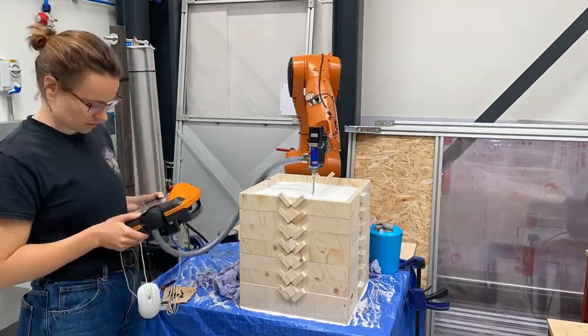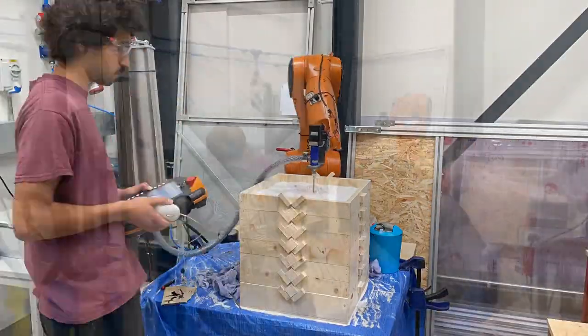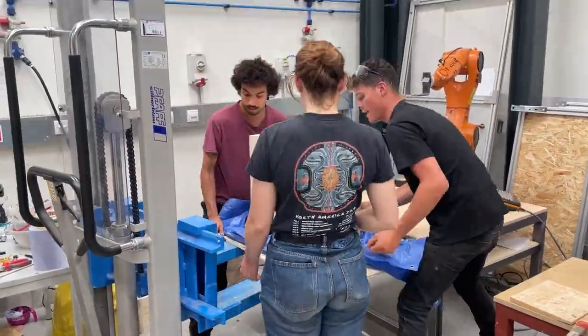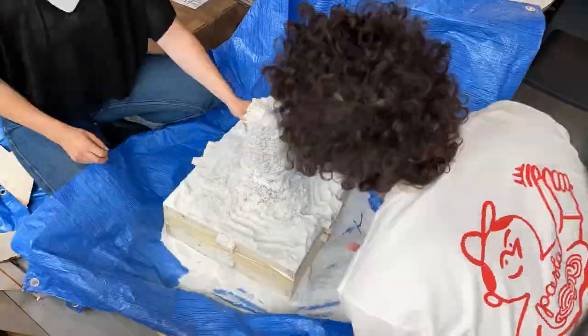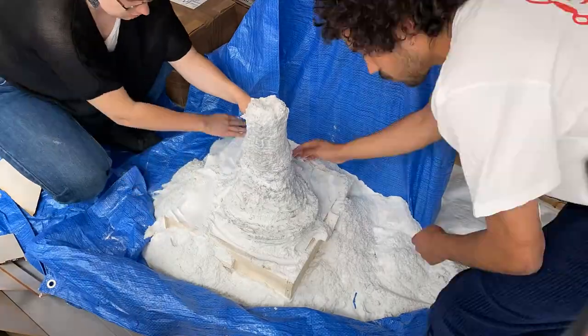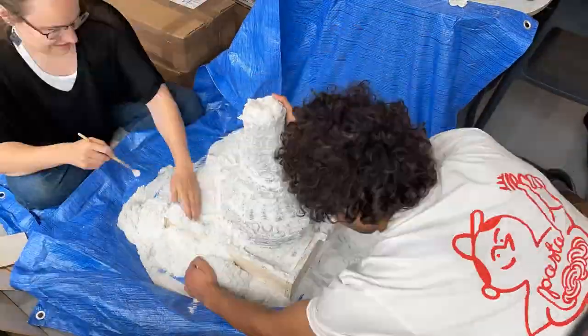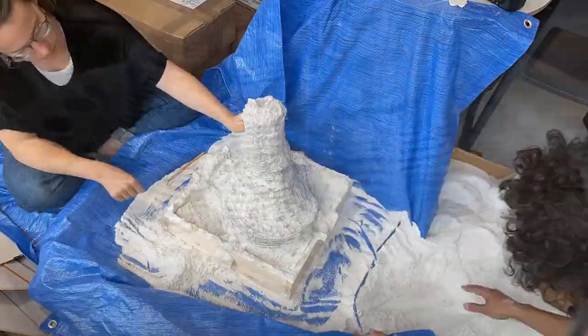in small sets, or chunks, of 12 layers. By stacking these chunks sequentially, we were able to reach print heights that would otherwise be impossible. After printing, we left the prototype to dry in place for 7 days. Once partially dry, we excavated the print and left it for a further 7 days until fully dry.